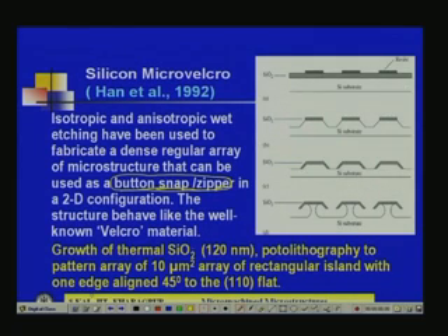So, here first silicon substrate, then silicon dioxide is grown, that can be done with thermal growth, then photoresist coating and patterning the photoresist. Okay. So, this step A is over. Now, after that you remove the silicon dioxide, then using the silicon dioxide as a mask material you go for etching of silicon. That silicon etching, that is silicon etch,